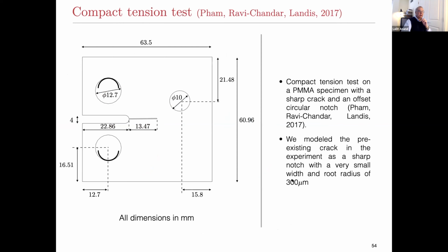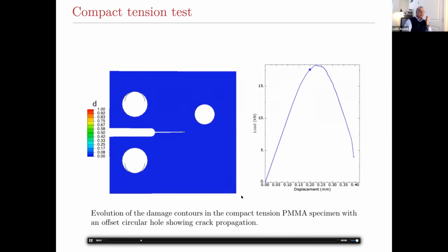One last example is from the work of Ravichandran and Chad Landis. They have this compact tension specimen with the sharp crack, but there's also another hole which is offset. In our numerical simulation, we modeled the sharp crack as a notch with a very sharp root radius. The root radius is 300 microns. So here's a simulation. That's the load displacement curve. And the crack is going to start to move towards the hole.